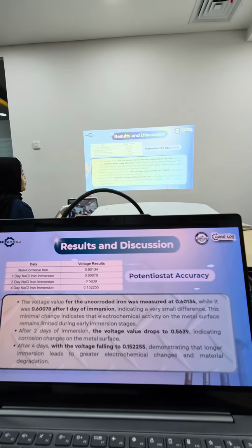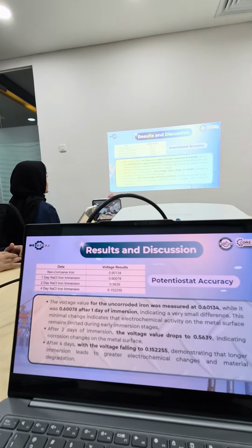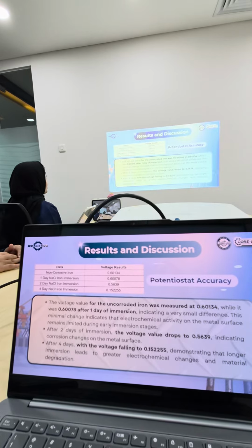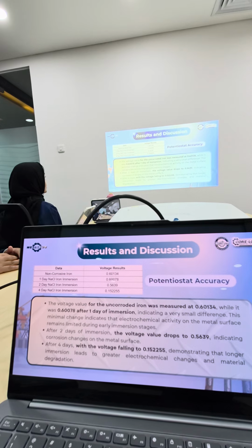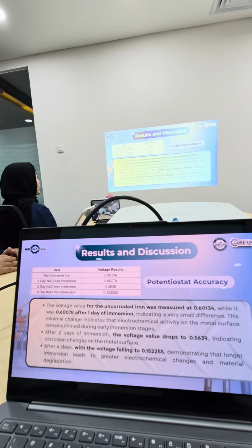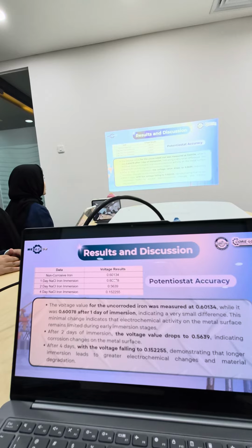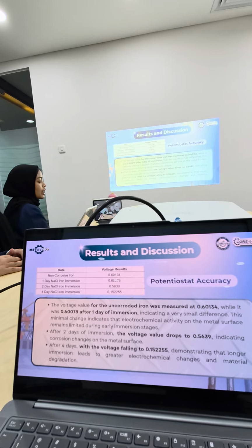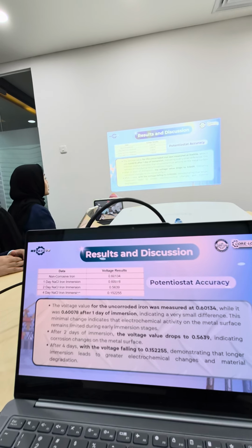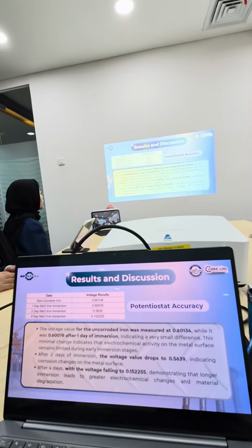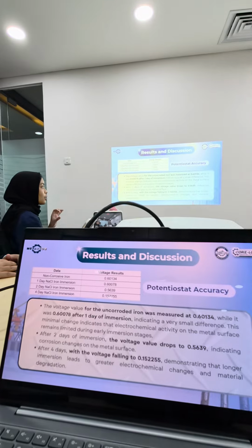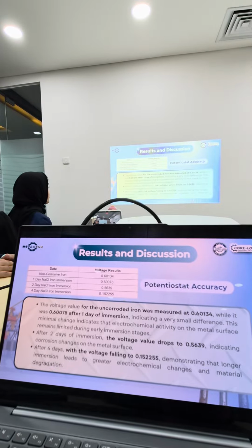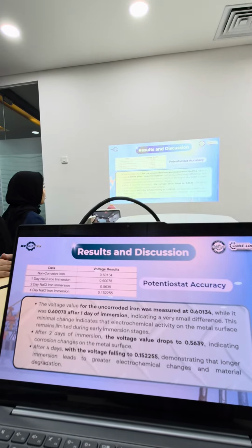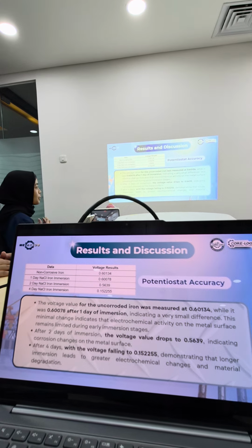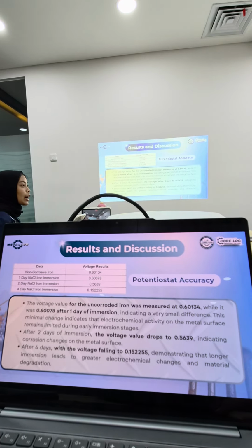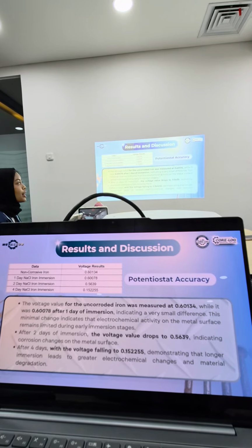Okay, now for the results and discussion. First, we evaluated the potentiostat accuracy by measuring the voltage results. The uncoated iron was measured at 0.60134, and it slightly decreased after 1 day of immersion to 0.60078. But after 2 days of immersion, there's a significant drop. The voltage value drops to 0.5639, indicating corrosion changes in the metal surface, but not really a lot of change in the beginning. But after 4 days, the voltage fell to 0.152255, demonstrating that longer immersion leads to greater electrochemical changes and material degradation, and also proving that our system can effectively detect and monitor the progression of corrosion.